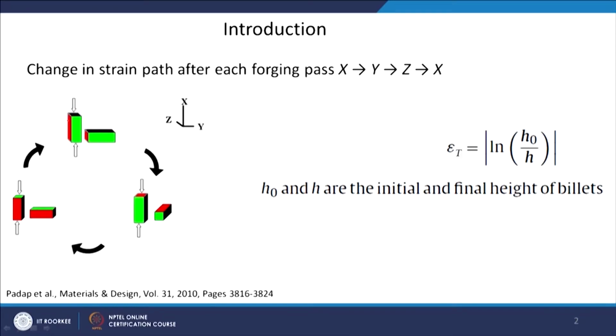So, the idea is that first, the three non-parallel surfaces of the sample are shown by three colors here: black, red and green. You first deform on the black surface, for example. What will happen if you are constraining in one dimension? There is an elongation of the material in the direction perpendicular to the red plane, because you have constrained the deformation in the direction perpendicular to the green plane. So, the lengthening is there, and the shortening is where you have applied the compressive deformation.